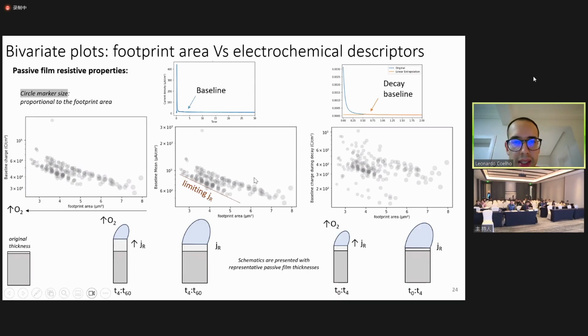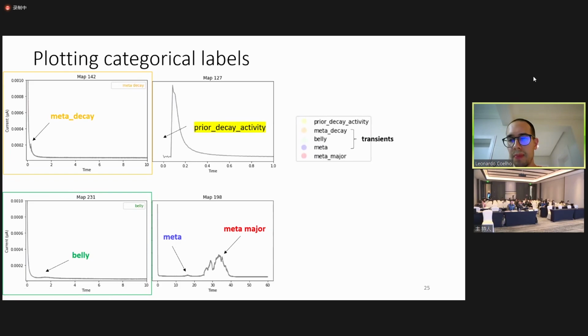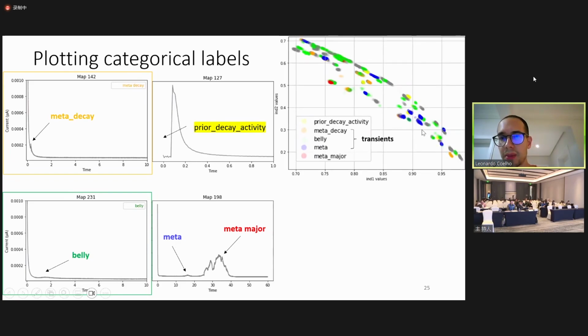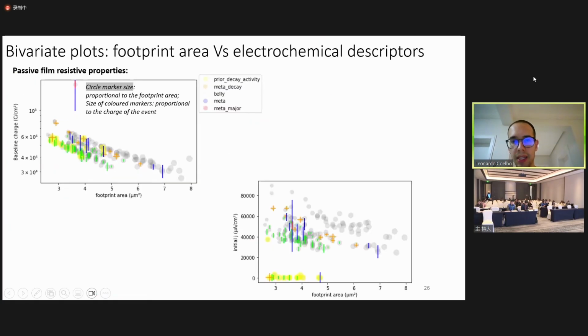And again, here I show you correlations of descriptors. There are very interesting findings. Once we embed the previously defined labels into the result, things become much clearer. We had only one case where we really have catastrophic failure. So this was even observed from the microscopy, this major event, and we were able to see that it belongs to, I would call it an anomaly or an outlier, if you will, in terms of grain orientation.